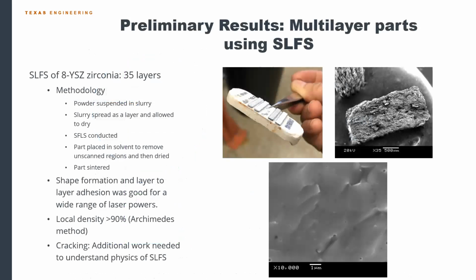So this slide just highlights the capabilities of this process. We are able to produce multi-layer parts. This one is a 35-layer part. And we can also make pretty dense parts. I think these are on the order of 90% relative density, but there are still some challenges to work out. The bottom SEM images show that there's some cracking still, which we're working on now.